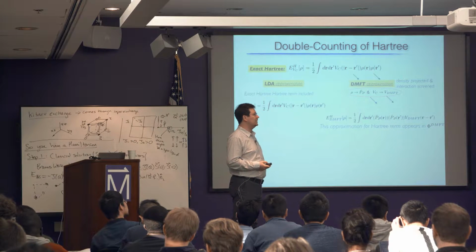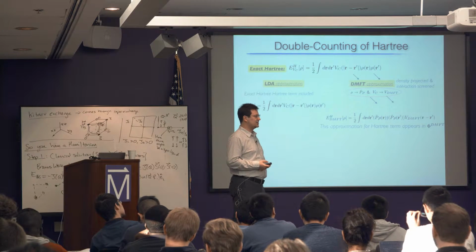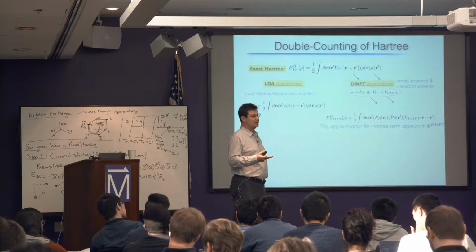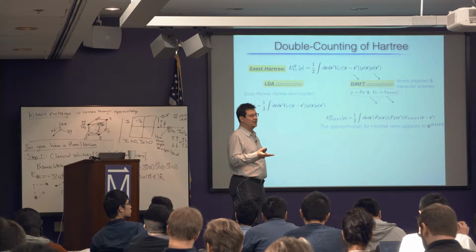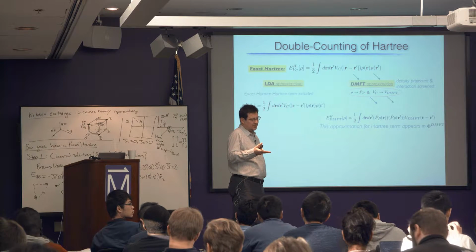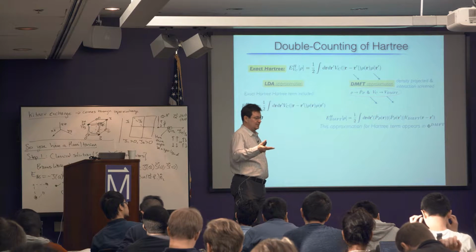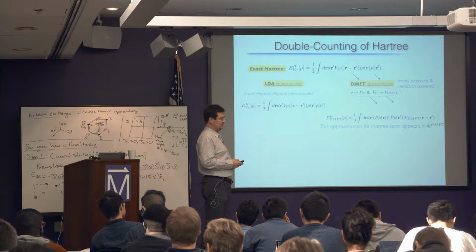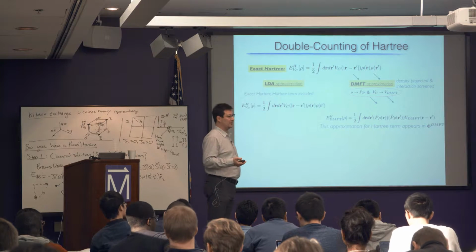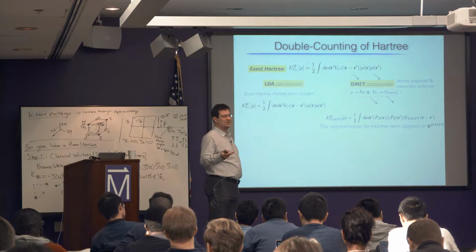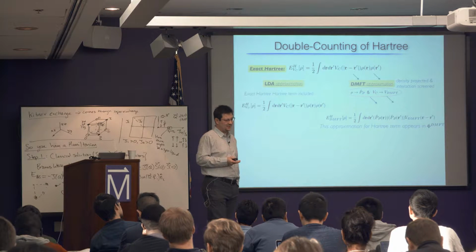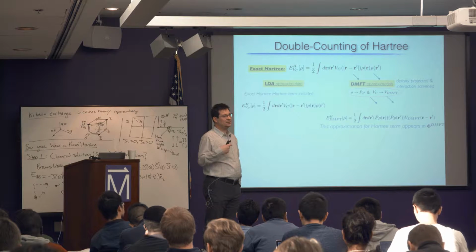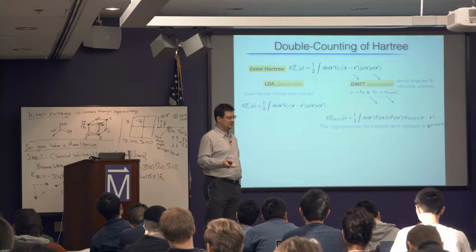Basically, the best way to get a decent estimation for the Coulomb repulsion is so-called constrained DMFT. So what you're doing is similar to constrained LDA, but you calculate the total energies with the DMFT approximation. So that's a different, decent way of estimating the screening. It's better than constrained RPA actually, because it turns out constrained RPA, which is used a lot in this area, is usually only qualitatively correct, but not quantitatively.